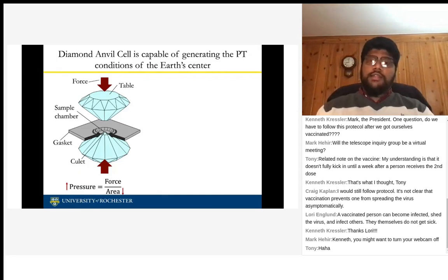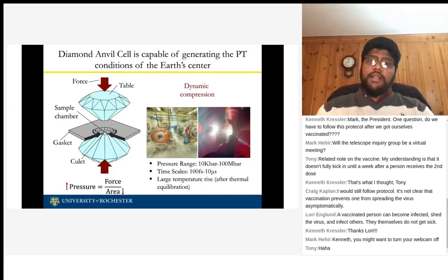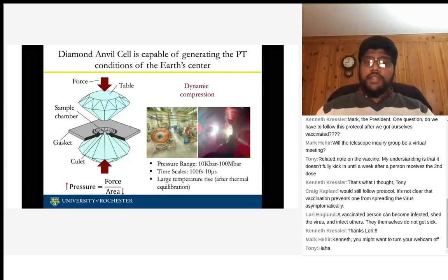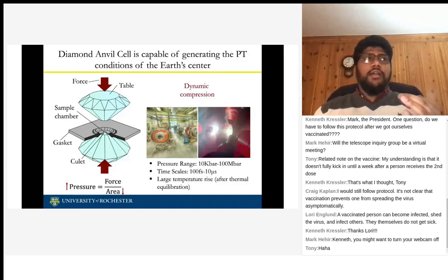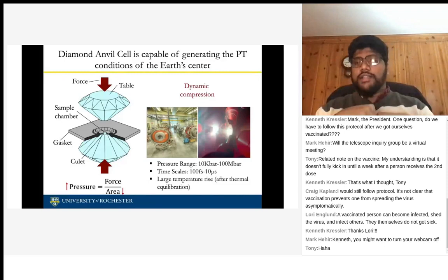And then the other way of doing it is using a shock wave. This is why Rochester is very famous, because of the laser lab, LLE. You have this laser that you use to shock a material so that you can go to really high pressure. We call it dynamic compression. In that way, we go to really higher pressures. But the one drawback is we are talking about a very short time scale, femtoseconds to microseconds. So it's a quick process, and also you have a large increase in temperature. So the time that you have to study the material is very limited in that sense. But you can have really bigger samples.